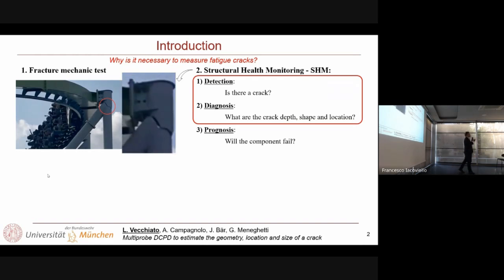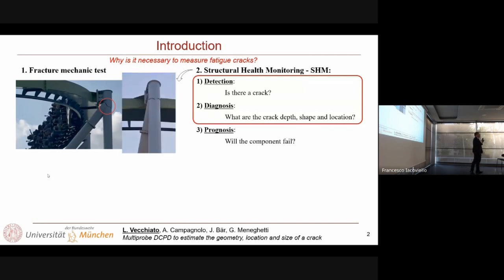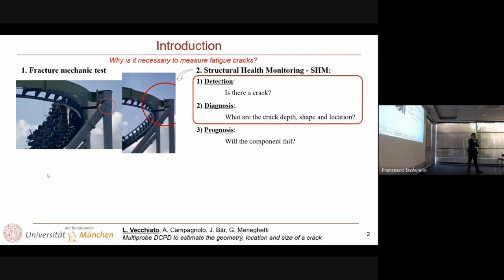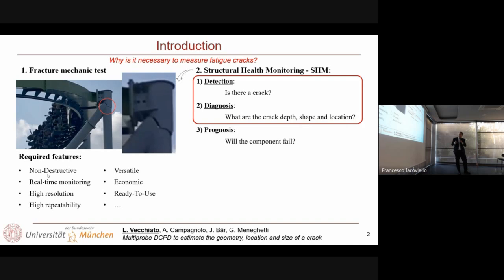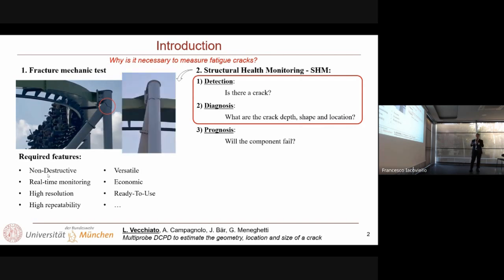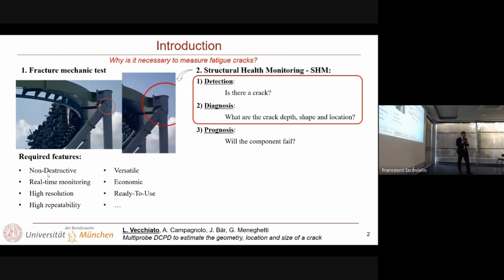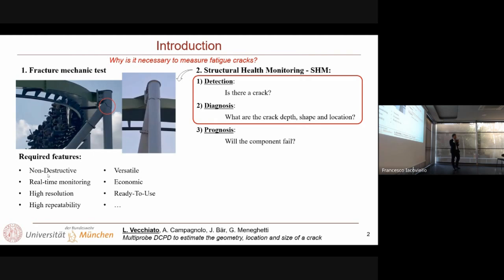So we want just to propose a new method for measuring crack propagating inside the material where we have no visual access to the crack front. When doing this, we have to deal with some required features from the experimental technique we can use to perform such measurements. In particular, such techniques must be for sure non-destructive. They should perform measurements in real time and locally in situ. They should have high resolution and many other features.